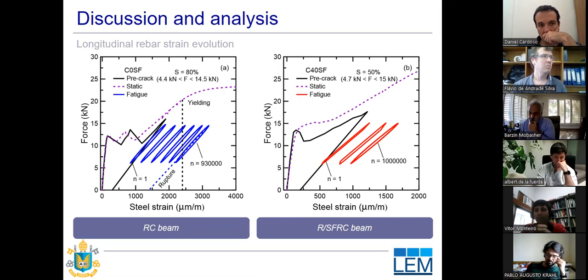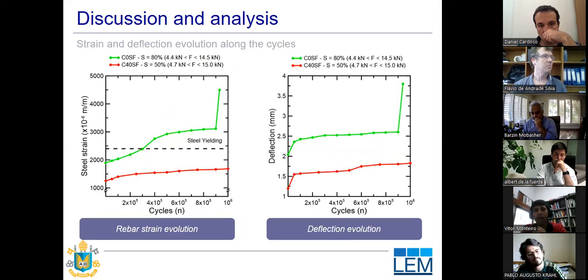So the fibers were successfully applied in order to mitigate the degradation of the rebars and prevent them from reaching rupture, even though they were at the same load level as the reinforced concrete without the use of fibers. So here we have the summary of the results of the rebar strain evolution. We can see that a major rebar strain evolution takes place when no fibers are added in the mix, until the beam reaches its rupture.